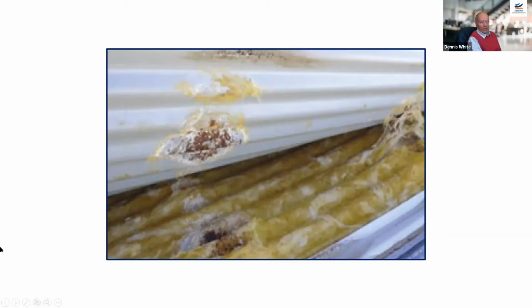Another problem is if you are wrapping the material for transport, and of course invariably it is tightly wrapped. If when it was wrapped, the air was fairly warm and the humidity quite high, you're trapping that moisture inside this bag, and effectively you're creating a steamer, which is detrimental to the cladding surface.